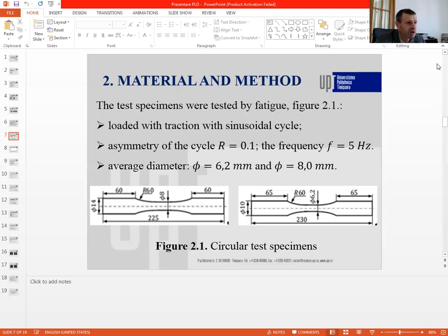Fatigue tests were performed on a 100 kilonewton Walter hydraulically operated machine. Two sets of circular specimens were tested, loaded in traction with a sinusoidal cycle having a degree of asymmetry of the cycle of 0.1 and a frequency f equal to 5 Hz.